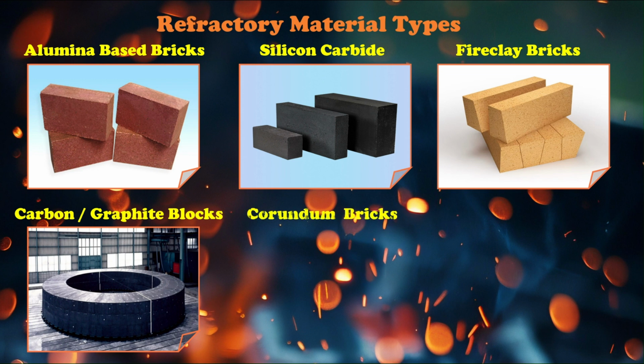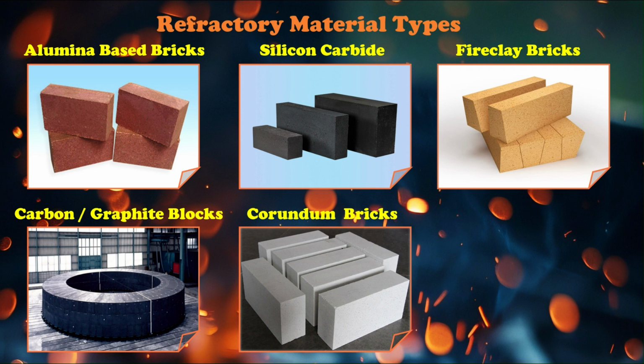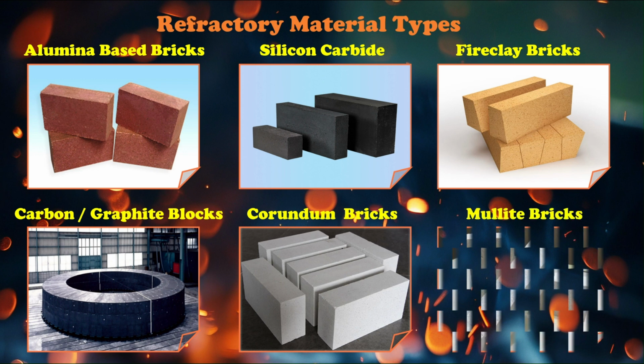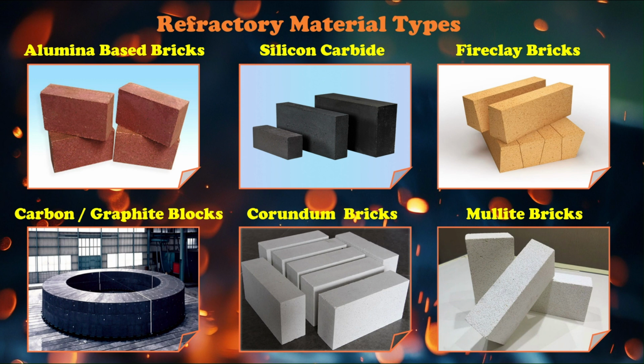Corundum bricks, high purity alumina. Used in the belly and tuyere zones for high wear resistance and corrosion resistance. Mullite bricks. Often combined with high alumina bricks in the bosh and tuyere zones for improved thermal shock resistance and corrosion resistance. Ceramic cup bricks. Plastic phase-bonded composite corundum bricks are used in the hearth bottom and tap hole areas for high refractoriness under load and corrosion resistance.